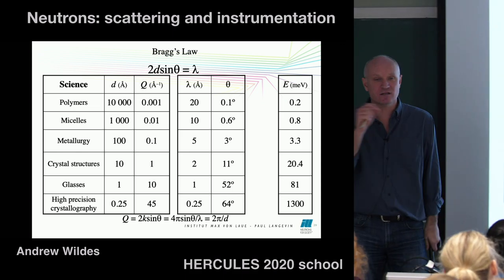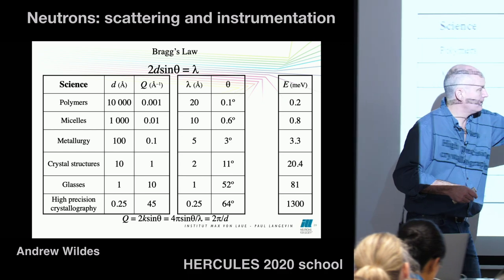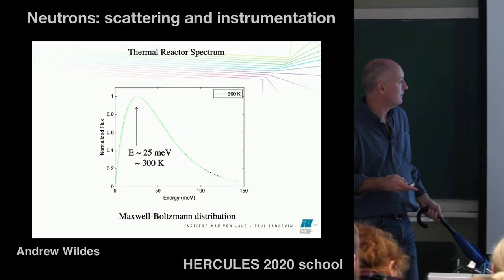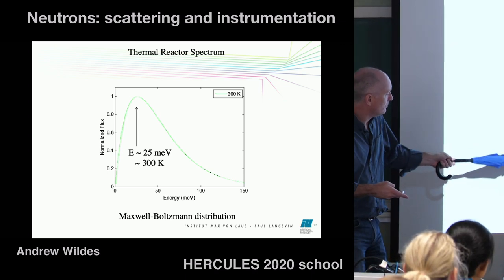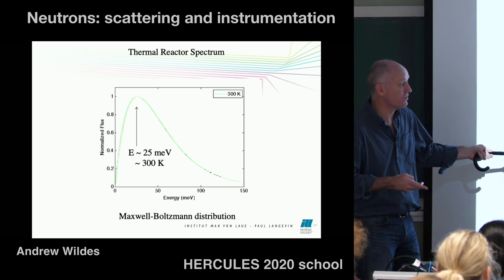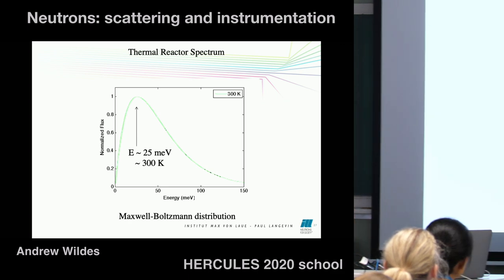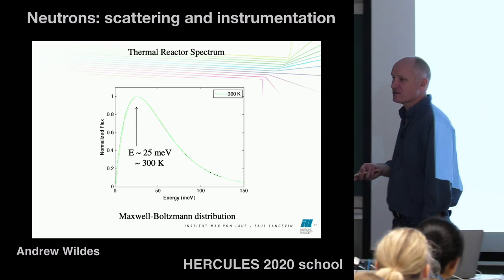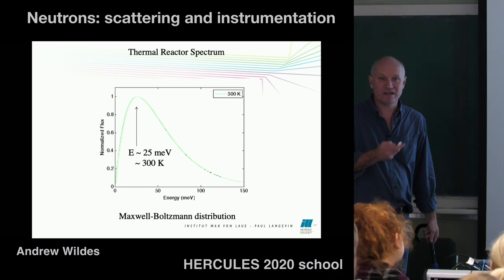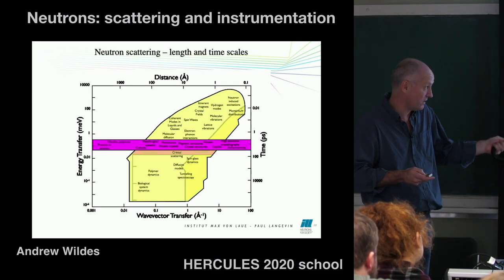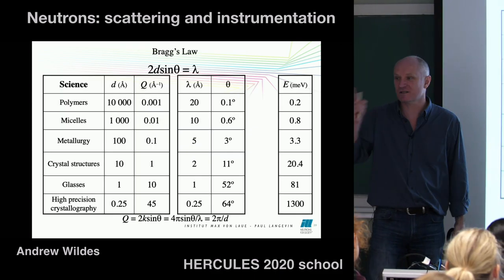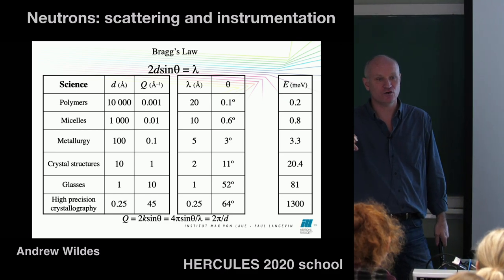And if you're only limited to neutrons that were about here, about 25 millielectron volt, and you look back at this table here, then you might be right down here for polymers where there's no flux, or you might be right out here for glasses where, again, there's no flux. So it becomes a very inefficient way to measure these types of samples if you stayed only with 300 Kelvin neutrons.